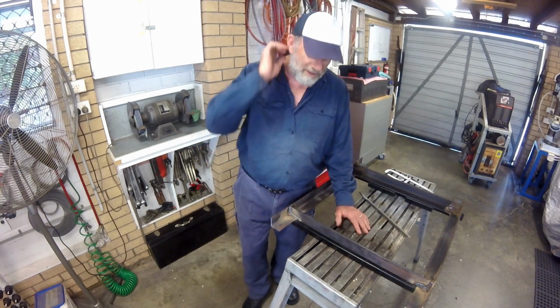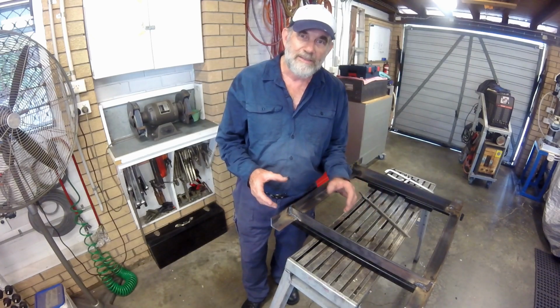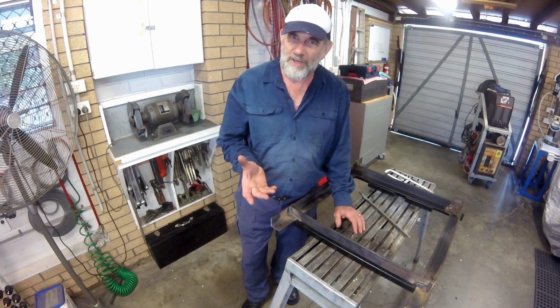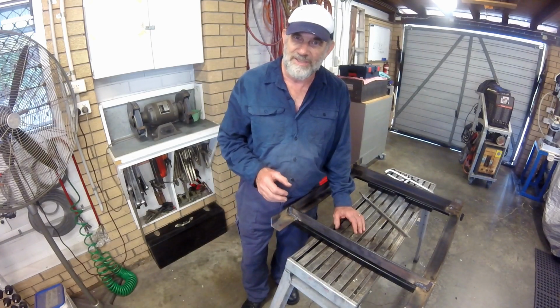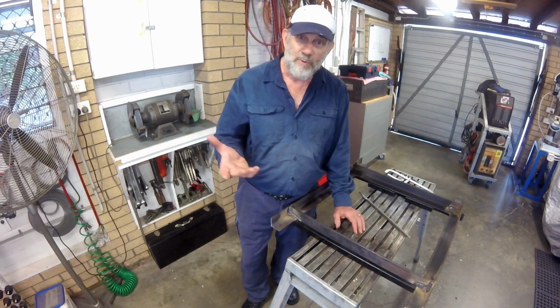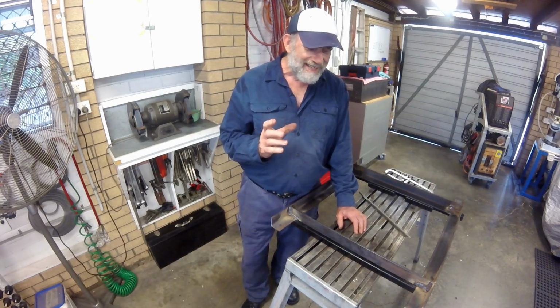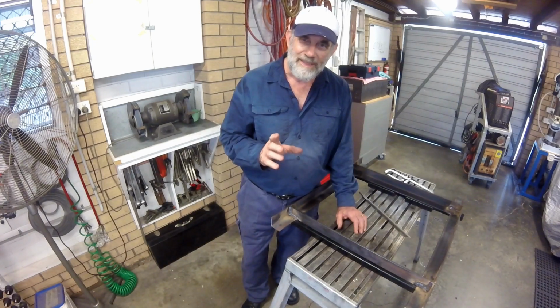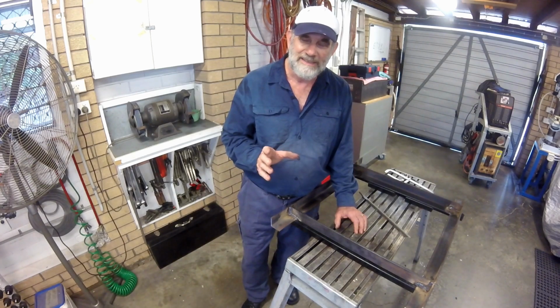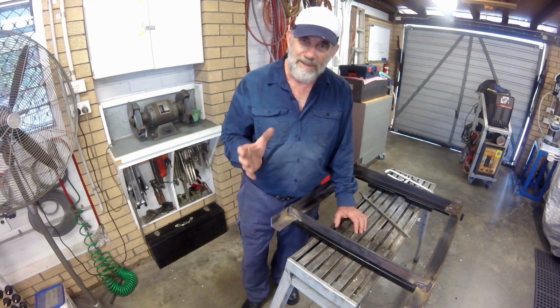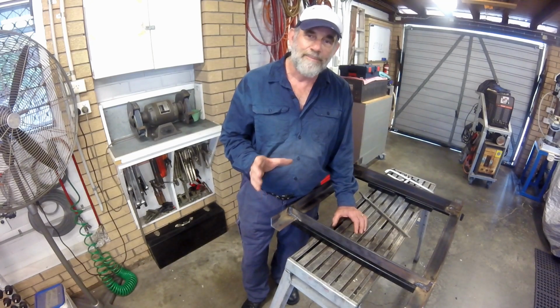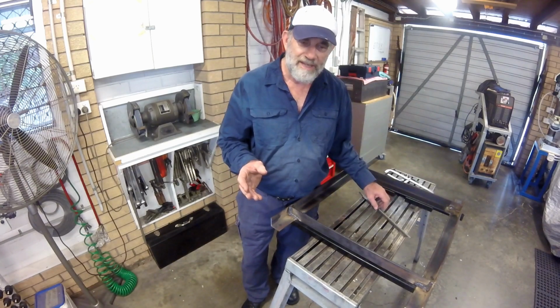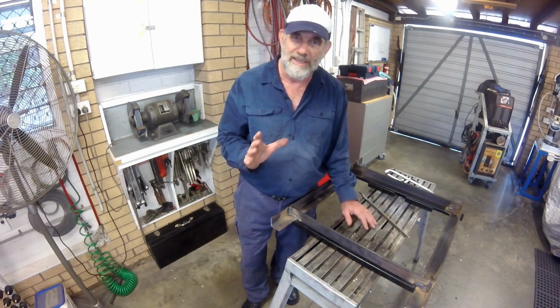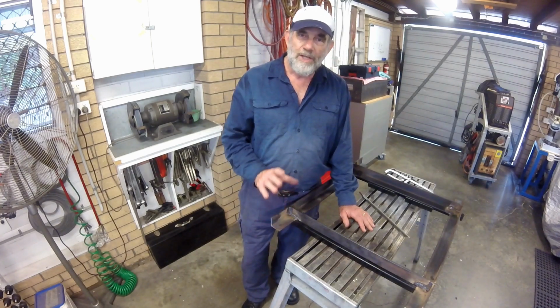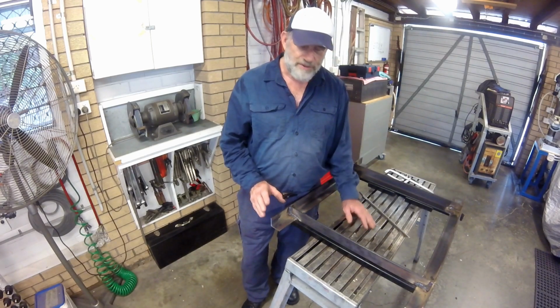And that's a little spot of slag in your weld, and the Lord only knows if there's one below the surface that you can't see, or an X-ray technician might know. But the rod I actually prefer to use, I just don't have in 1/8 or 3.2mm size, which is an E6012, 6012 for tacker, and so I do have the remnants of a box of 6013s, and that's what I've used here.